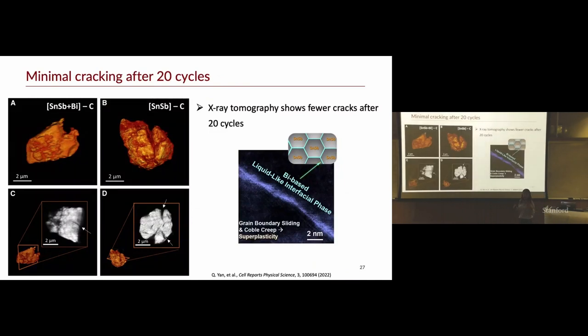So we also were able to do this in 3D. So we can do 3D imaging. I showed you one example of that on the nanoscale. It's hard to do 3D imaging in a real operating battery. It's possible, but hard. So here we wanted to get really good data, so we actually just harvested the batteries. And so this is just looking at two different particles, one with the bismuth on the left and one without the bismuth on the right.